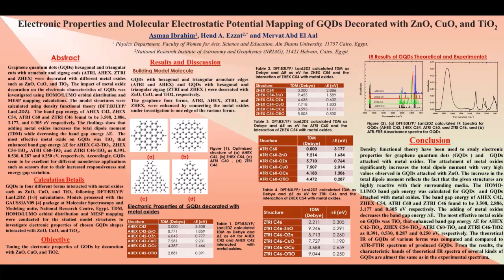Graphene quantum dots, hexagonal and triangle cuts with armchair and zigzag ends, were decorated with different metal oxides such as zinc oxide, copper oxide, and titanium dioxide. The impact of metal oxide decoration on the electronic characteristics of graphene quantum dots was investigated using HOMO-LUMO orbital distribution and molecular electrostatic potential mapping calculation. The model structures were calculated using density functional theory.